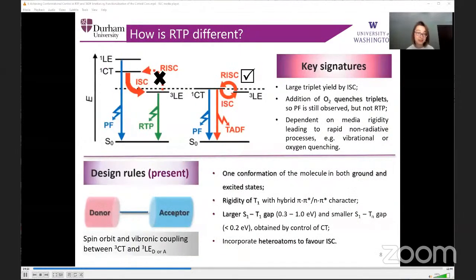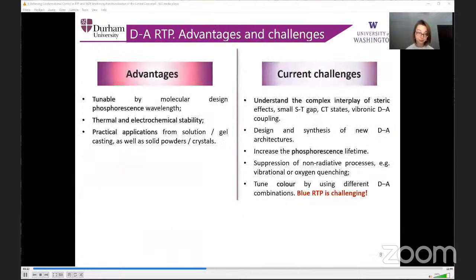So how is RTP different? In terms of the molecular design, we are still looking for the orthogonally linked donor and acceptor structure. However, we want to incorporate heteroatoms to favor intersystem crossing, because this is exactly what leads to the RTP emission. Also, we are looking for a rigid first triplet state with a hybrid pi-pi* and n-pi* character, and preferably one conformation of the molecule in both ground and excited states.